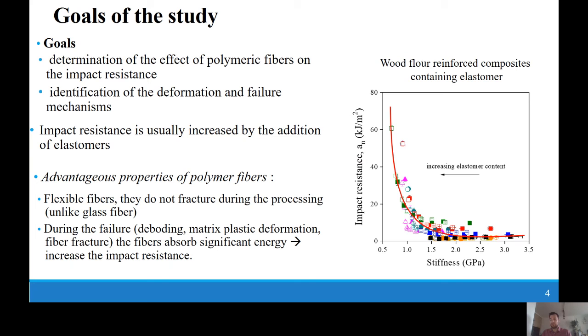It is clearly visible in the figure that the impact resistance is decreasing as a function of stiffness with increasing elastomer content in the case of wood flour reinforced composites. On the other hand, fiber modification usually results in the simultaneous increase of stiffness and strength. Another important thing is the advantageous properties of polymer fibers. So these fibers are flexible, they do not fracture during processing, but during failure, these fibers absorb much energy by the occurring micromechanical deformation processes, which result in increased impact resistance.